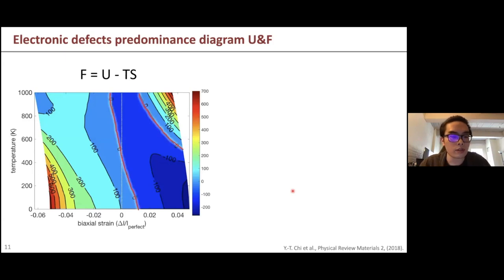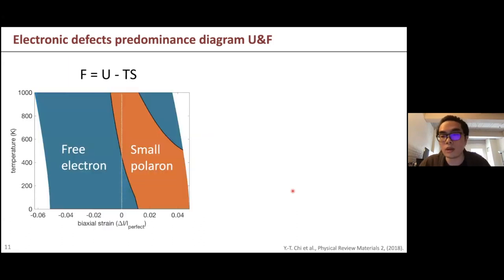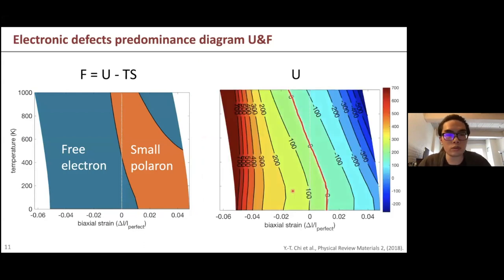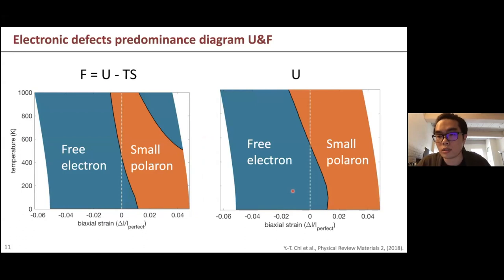And then by finding the zero energy, meaning they are the same, we can basically make the predominance diagram this way. If we look at the internal energy, the only difference between these two energies is the entropy term. So it's very clear, and it makes sense that at higher temperature, the species that have higher entropy will dominate, and free electron has higher entropy.